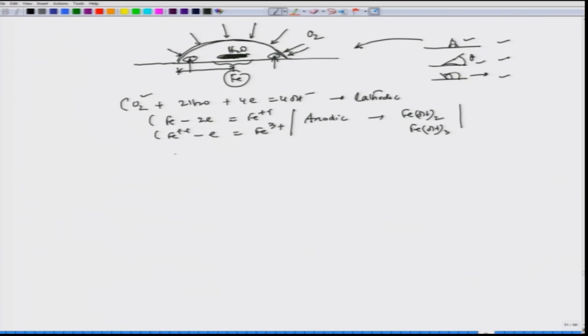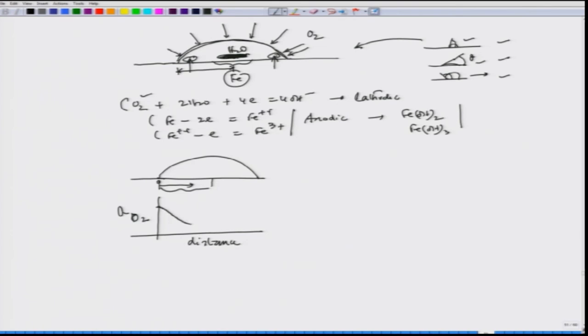So, now if I see the plot of oxygen concentration, from this to this, if I try to see the oxygen plot, this is the distance and this is oxygen content. If I see the concentration or activity of oxygen, then at this place the activity would be the maximum. And then as we go from this to this, as the reactions are progressing, we are elapsing time. So, the oxygen content in this zone would get depleted. In this zone, there will be supply of oxygen from the surrounding air. So, oxygen concentration gradually goes down.